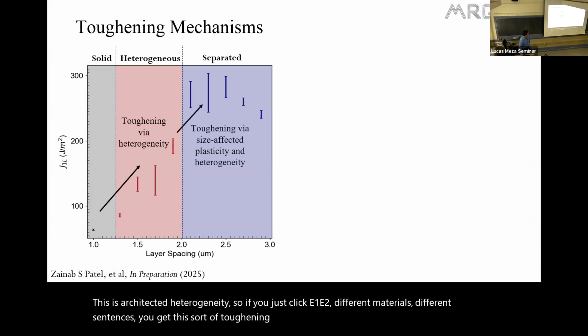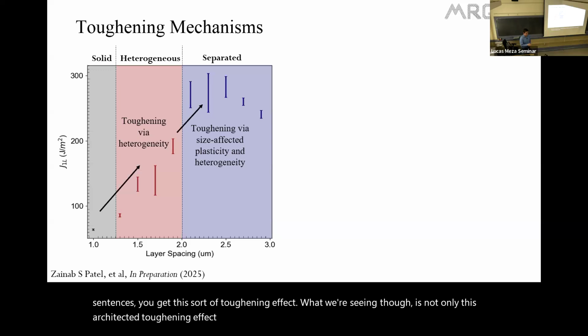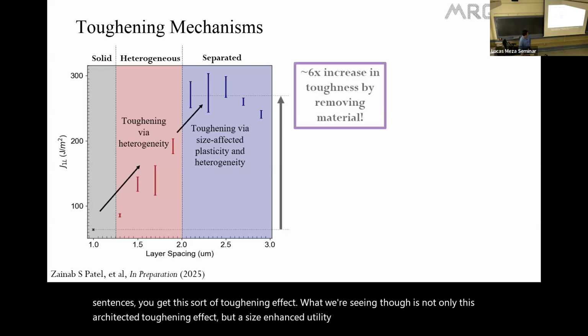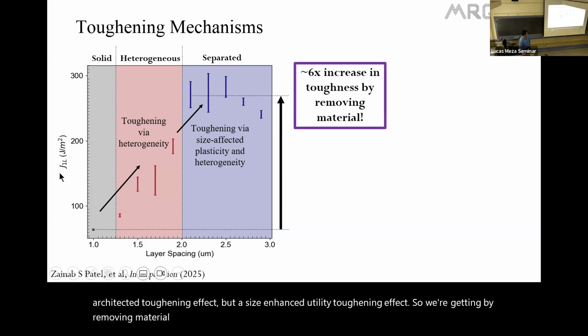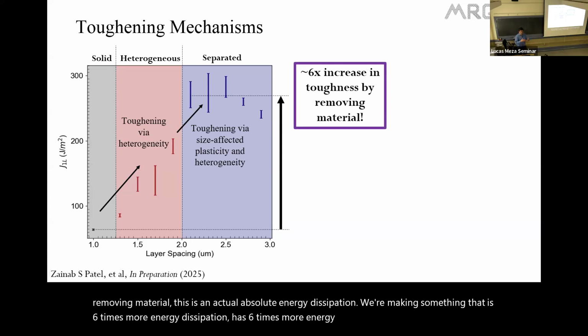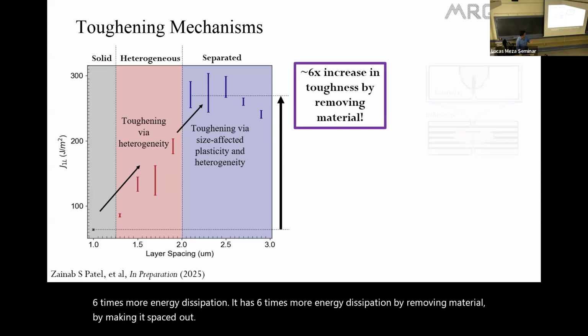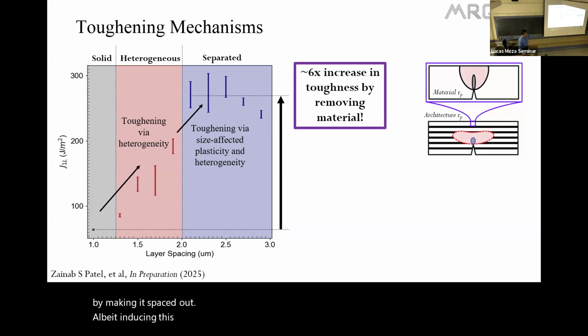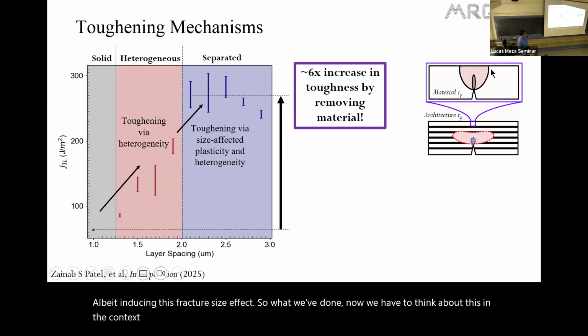What we're seeing, though, is not only this architected toughening effect, but a size-enhanced ductility toughening effect. So by removing material, this is an actual absolute energy dissipation. We're making something that has 6 times more energy dissipation by removing material, by making it spaced out, all by inducing this fracture size effect.